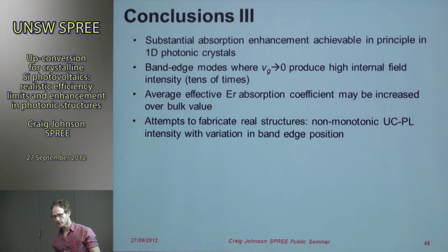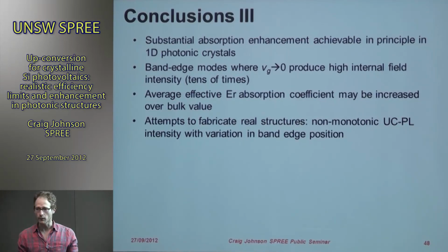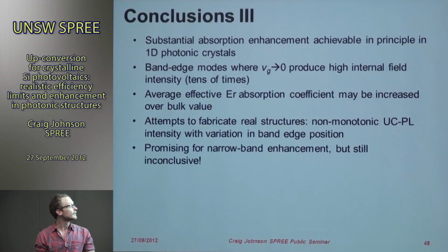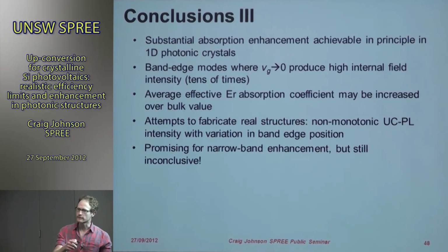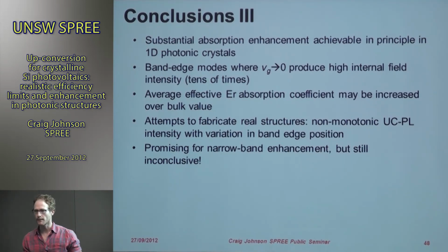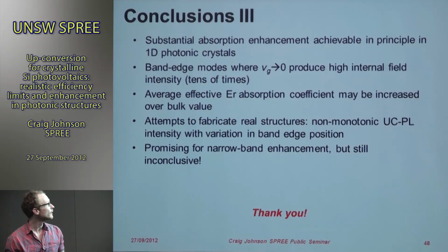So attempting to fabricate real structures had its challenges, of course, but we saw non-monotonic PL intensity with a variation in the band edge position, which is really what we were trying to look for. It's an indicator that something promising is happening, and it's promising for narrowband enhancement as well, for a whole range of applications. But it's inconclusive what exactly is driving it and what the real dynamics are in terms of things like saturation and so on.